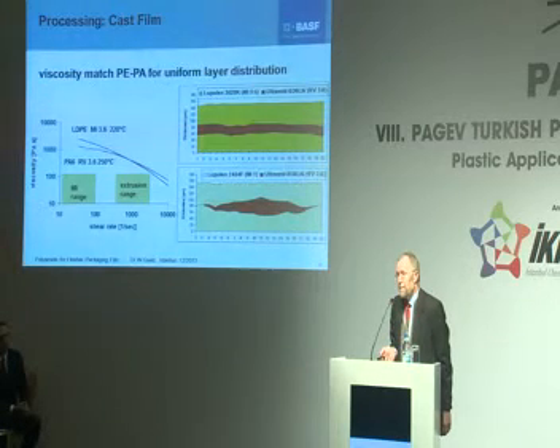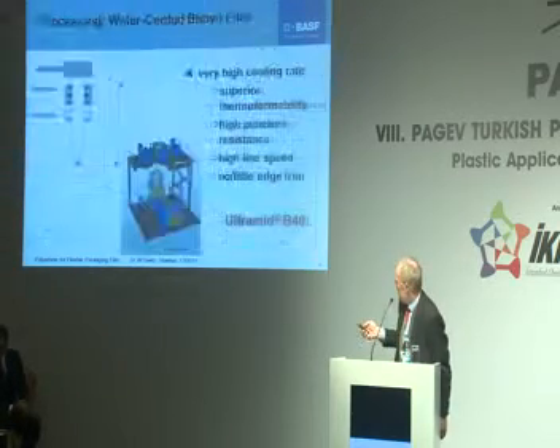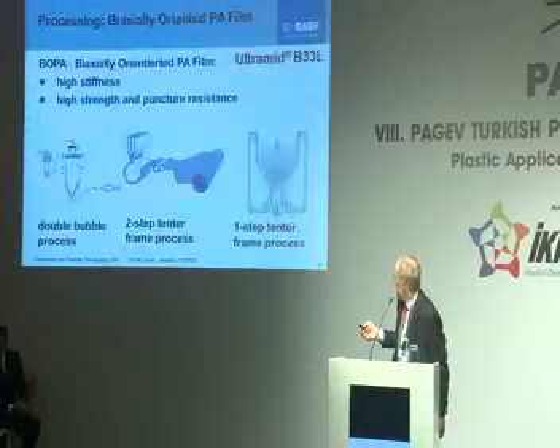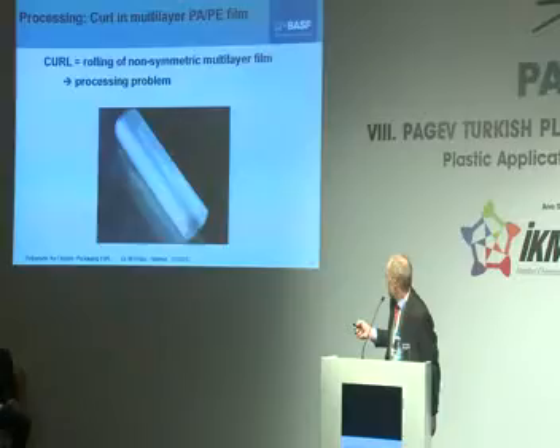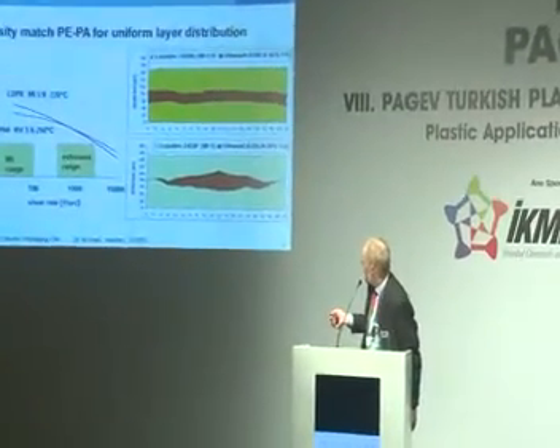The low viscosity component will go preferentially to the edges of the cast die, as shown in the bottom film, where the low viscosity polyethylene is enriched in the edges and the higher viscosity polyamide is concentrated in the center, whereas with a viscosity match between the components, the polyamide and polyethylene thickness is more or less uniform across the width of the cast die.